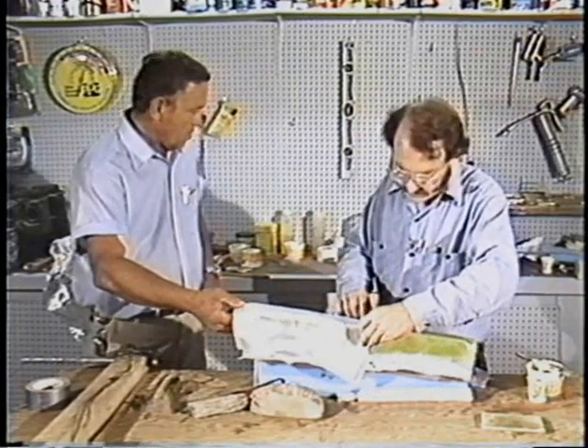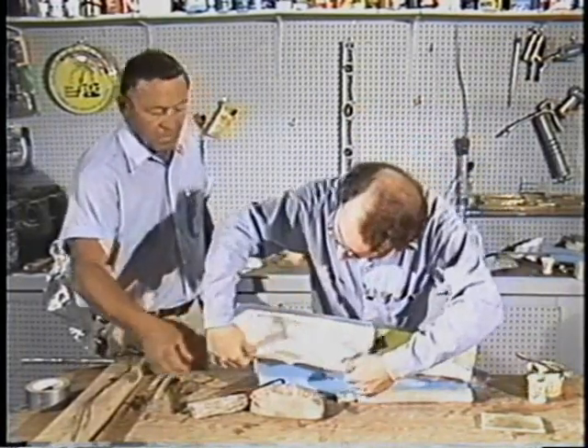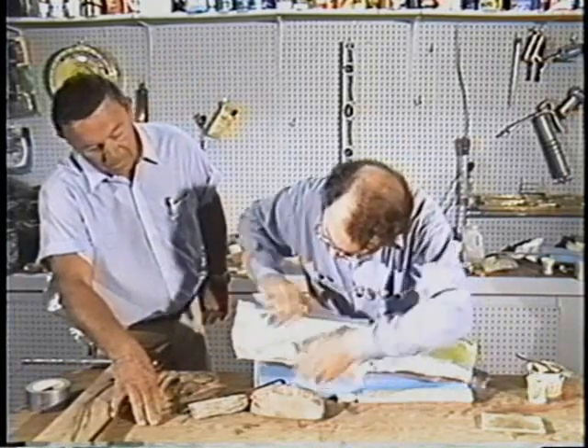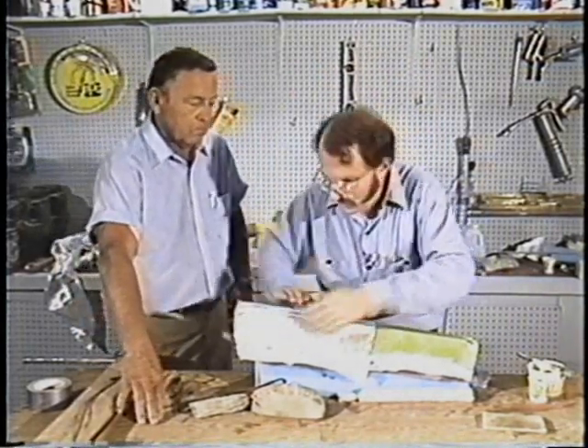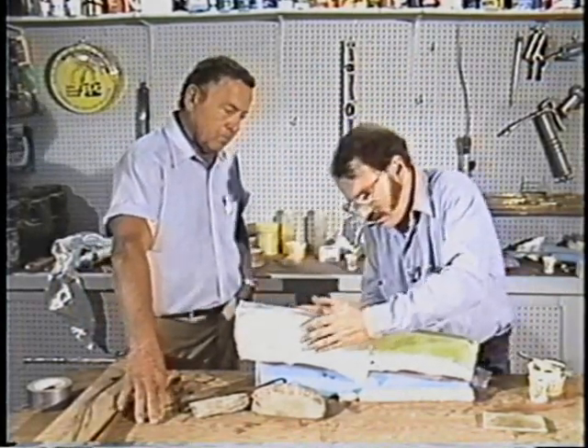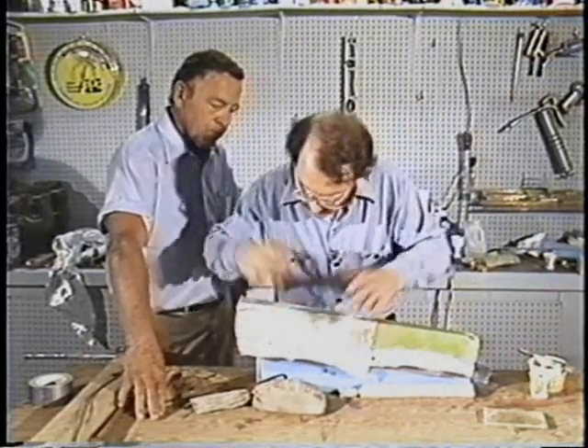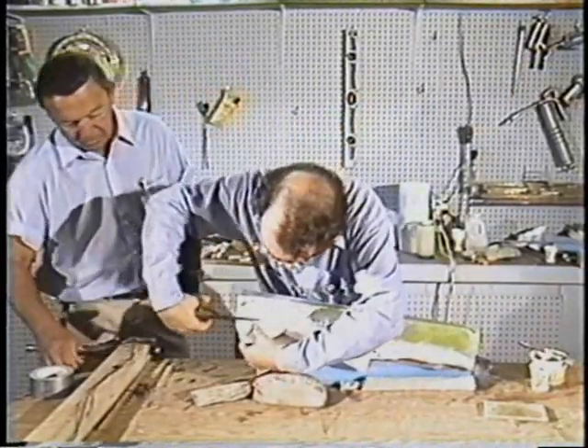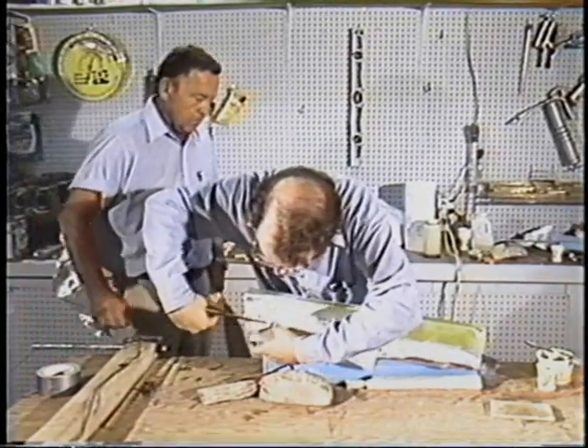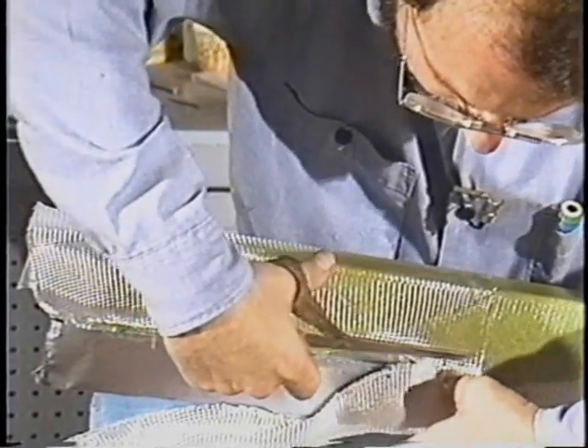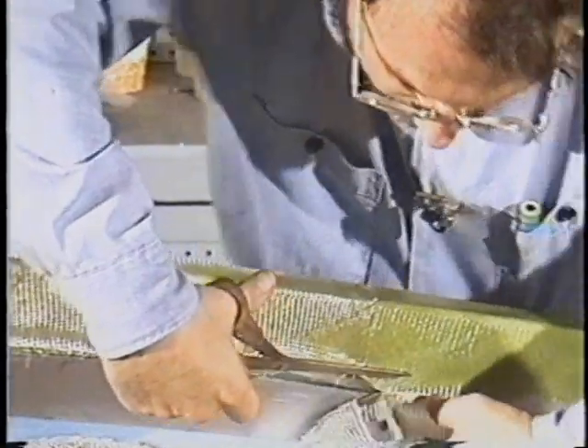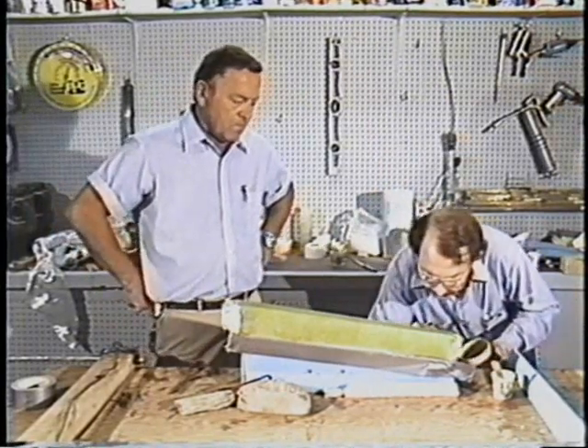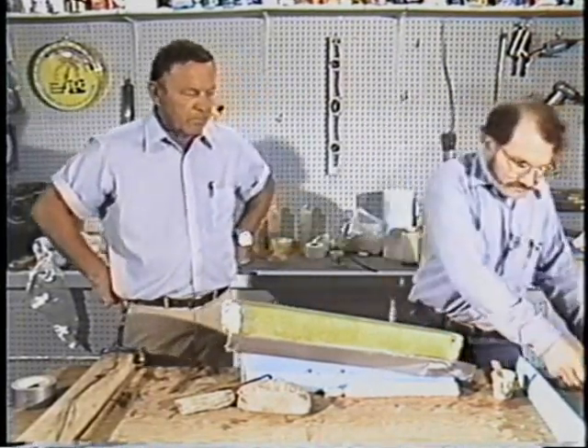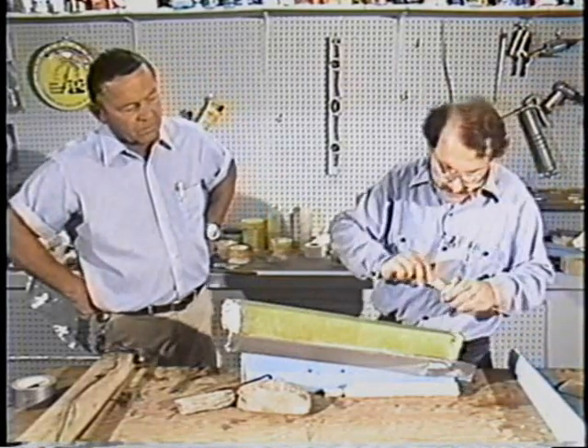Notice that the second ply of the cloth is a little more than half the length of the first ply. This is another advantage of composite construction. Because the root of the airfoil will be subjected to higher stresses than the tip, we can beef it up with an extra ply while saving that weight on the tip where it isn't necessary. Once we've positioned the second ply, we'll trim the edges on both sides of the airfoil. In this case, it's best to trim them just a bit short in order to prevent a ridge in the airfoil. After we have wet out and squeegeed the final ply, we are ready to join the leading edge back into place on the airfoil.